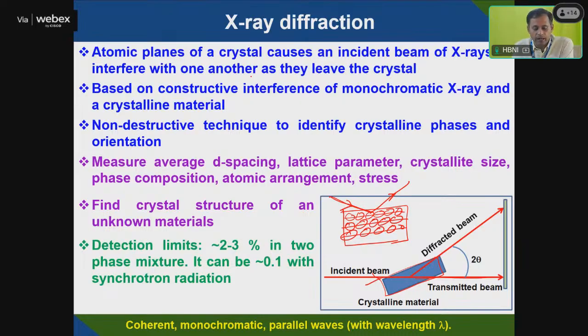So the atomic planes of the crystal cause the incident X-ray beam to interfere with one another as they leave the crystal. They will interfere with these atoms and they will come out. Based on whether it is constructive interference or destructive interference, you will get the diffraction peak. It is a non-destructive technique, so in XRD you can recover your material. Mainly you identify the crystal phase and its orientation. It measures the d spacing. You can get d spacing, lattice parameter, crystallite size, phase composition, atomic arrangement, stress, etc.